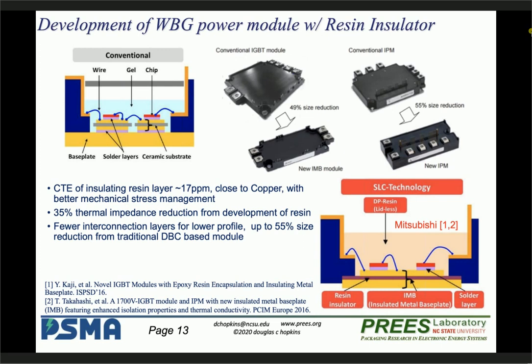And you'd want the copper thin. What happens is if I have no copper, I have great thermal conduction, but I have very, very poor current spreading. If I keep increasing the copper, then I get more two-dimensional spreading of current. But if I made the copper, let's say, 3 inches tall, I'm not spreading anymore. I've done all the spreading I can do in the first 2-3 millimeters, and the rest is strictly thermal resistance. So there's an actual optimum for copper, and it depends on what your thermal conductivity of isolation layer is, if you're doing a sandwich, of how thick copper you want for your current distribution and for your thermal spreading. And if you go above that, you only add thermal resistance.